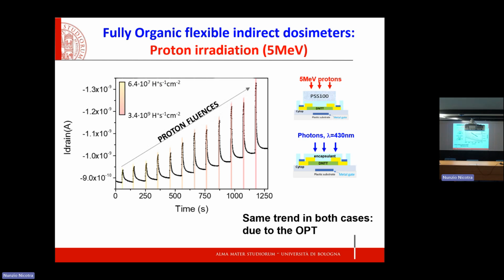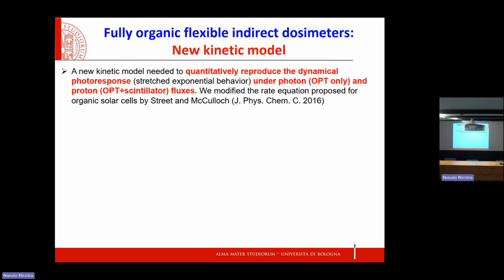And you would think, okay, there is a baseline shift, something is happening, a degradation of my material, whatever. But we see exactly the same response of the full device under protons here, and of the phototransistor alone under photons. So it is not related to a damage induced by the protons, but it is intrinsic to the response of this organic semiconductor, which is controlled by trapping states, where trapping states have a strong role.